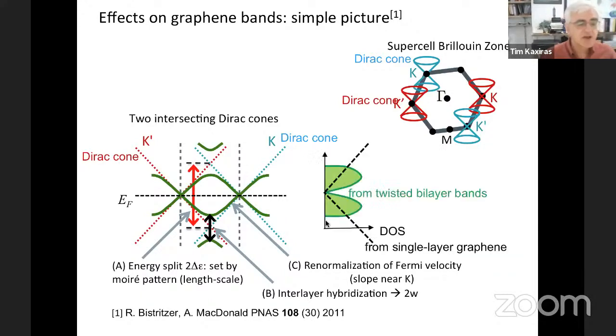And here's the density of states, again, a really crucial feature of the system. So the green lines now, the green density of states comes from the green bands, and the dashed line is the original straight line from the single layer graphene. There's of course two of those, and those are very different. The scale of this is very different, and you see now a large density of states produced by these flat bands.